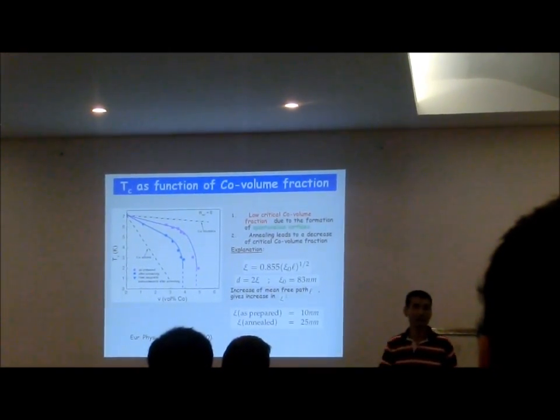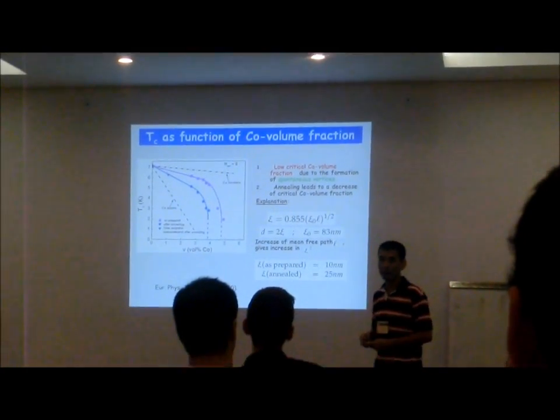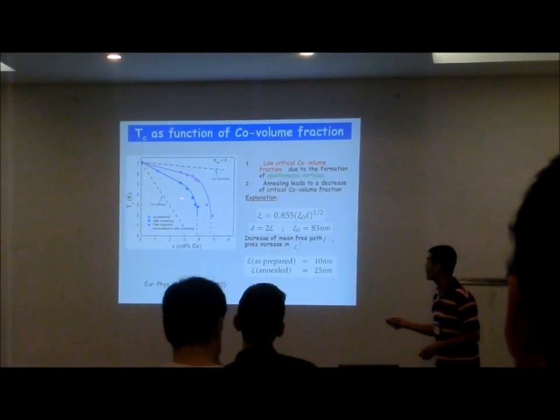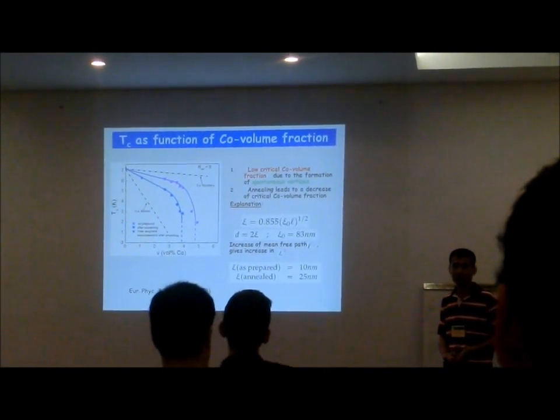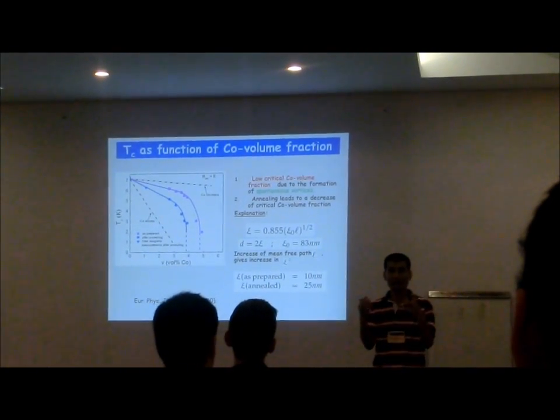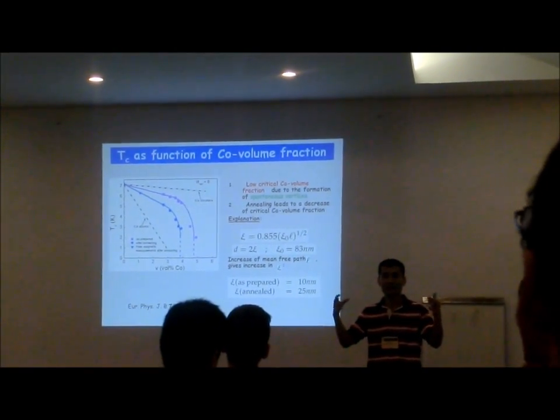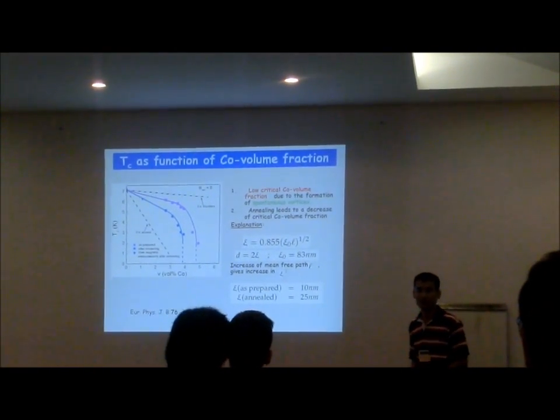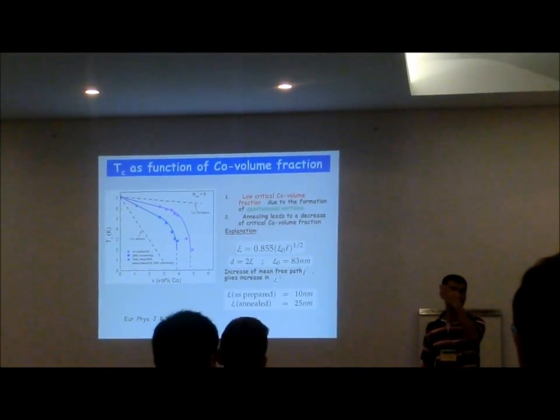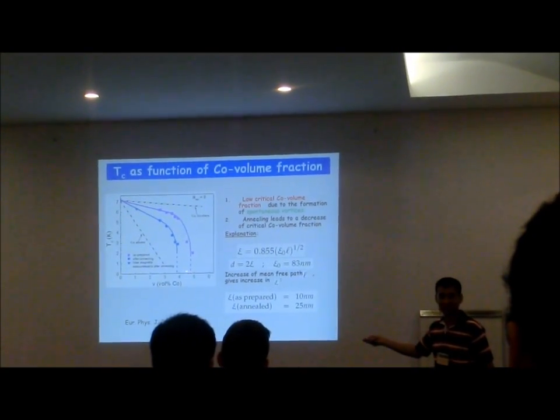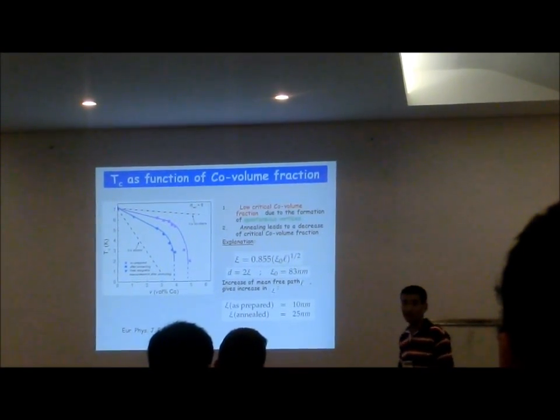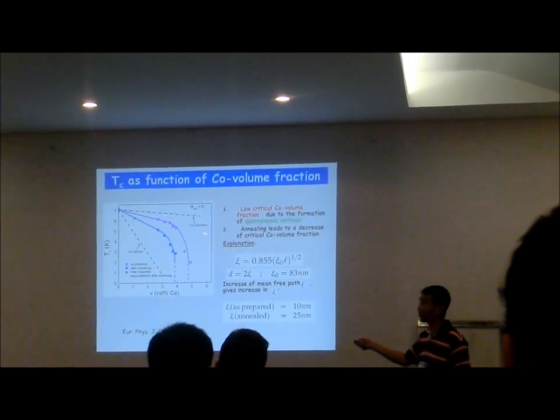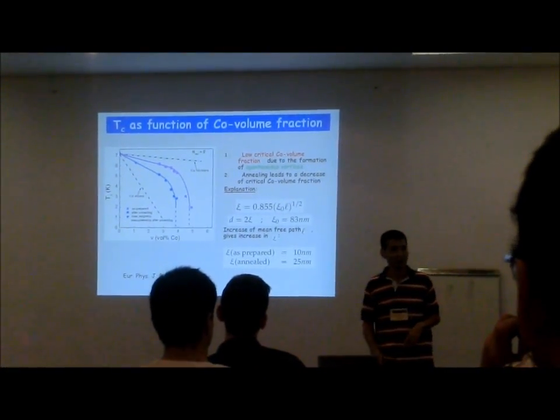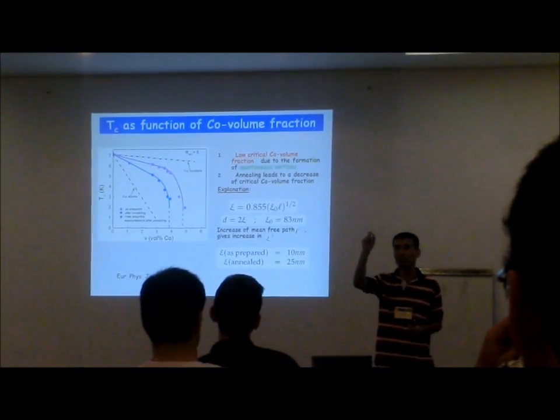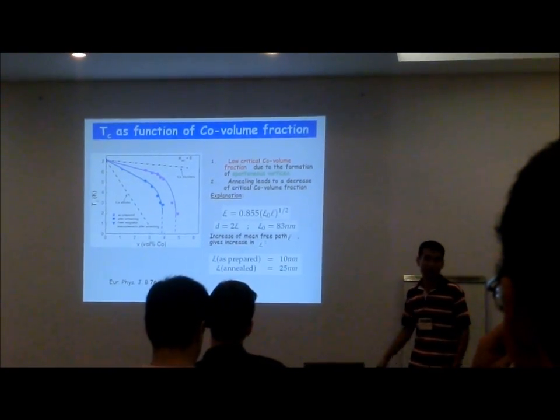This field has very sharp transition. It's like a 3D percolation problem. But our sample is very different because of the formation of spontaneous vortices. So the effective volume increased a lot. It's not only the cobalt particle, but really the vortices. So we don't need a lot of cobalt particles to kill the superconductivity. We just need only 7%. But if we really compare with the cobalt atoms inside the lead, the effect of cobalt atoms is much stronger. This is due to the spin flip, the pair breaking of cobalt atoms.